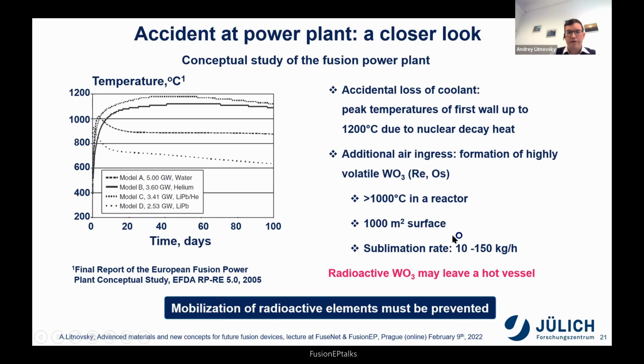And if we calculate, according to our data, the amount of this volatile aerosol, supposing the same surface area as presently in ITER, in DEMO, in this fusion power plant, we can deal with 10 to 150 kilograms of radioactive tungsten per hour escaping the vessel during an accident. And of course, nobody wants to have this. Now, with all these conditions, with destroyed logistics and so on, if we had a chance to make a kind of inbuilt safety in our material that will react to the accident without any action from a human being, it would be a nice opportunity.